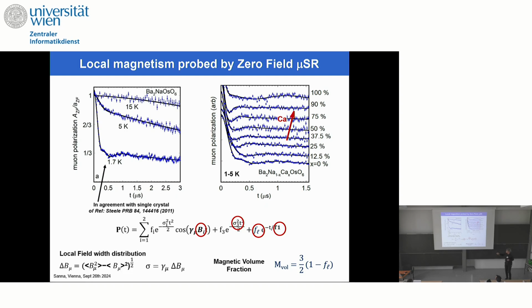The fitting function contains different contributions, some oscillations, plus a very fast decay contribution, which is where the physical information is. Here, the exponent is related to the distribution of local fields as seen by muons. What does it mean? It means that part of the signal in these materials, depending on the implantation site of the muon, doesn't see a coherent oscillation, coherent precession of muons, which means that you have a sort of electronic disorder.